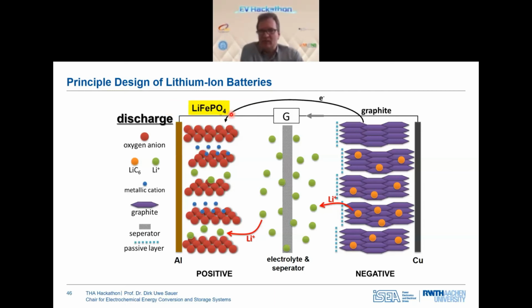Another quite popular material is lithium iron phosphate, LFP, which is another version for the cathode material. But please be aware that the anode, the graphite anode, still remains the same. And the anode, for example, is mainly responsible for the lifetime. And therefore, if you just keep the graphite in the same amount as with an NMC battery, you will not get more lifetime with an LFP battery.